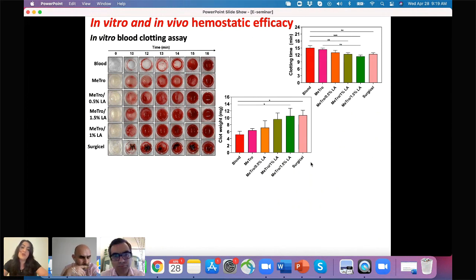So we start with an in vitro experiment. This is a standard in vitro blood clotting assay where we expose different formulations of the biomaterials to fresh human blood. We have our control samples where there was no biomaterial in the wells, and then we use MeTro with different concentrations of laponite, and we also use Surgicel, which is a commercial hemostatic agent. And then once we expose fresh blood to these formulations, we measure the clotting time. We also collected the clot from these wells, and we measure the weight of the clot.